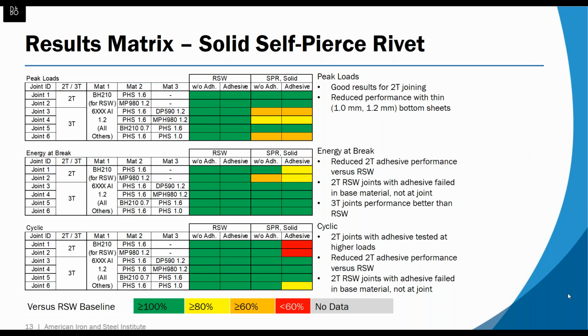There's a peak load table where we measured the maximum amount of force experienced in pulling the joint to failure. The second table is the energy at break table, which is the total energy absorbed going through failure of the joint. Finally, the cyclic is the comparison at the 100,000 cycle load between the resistance spot weld and the mixed material joint.